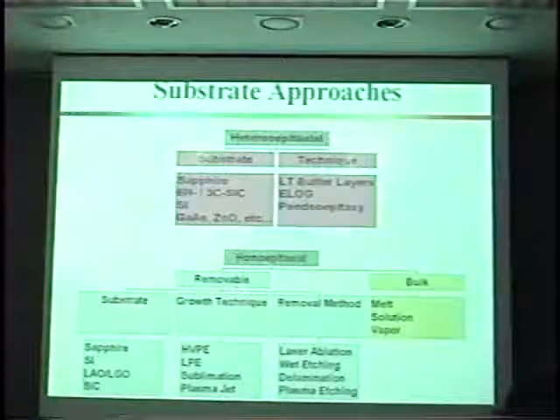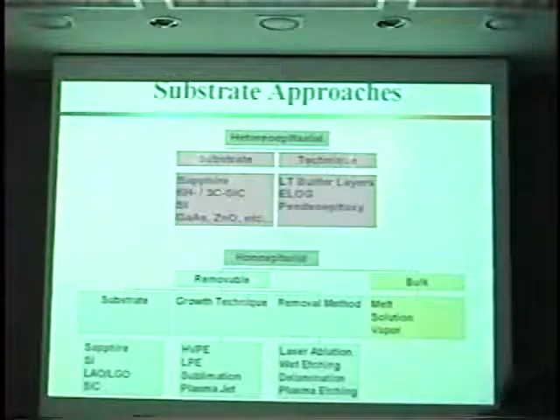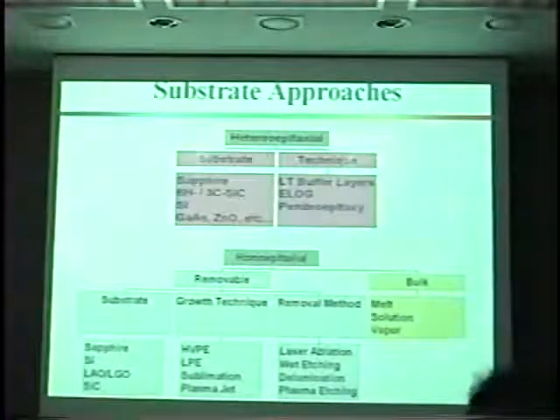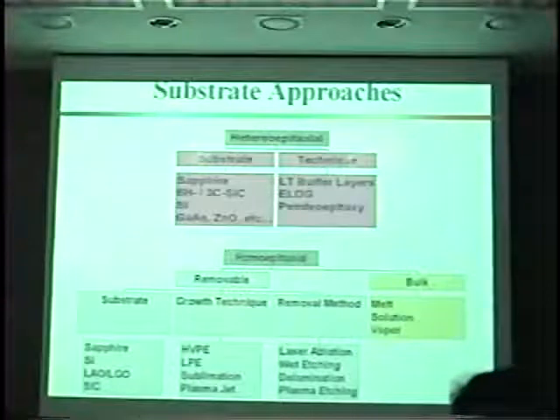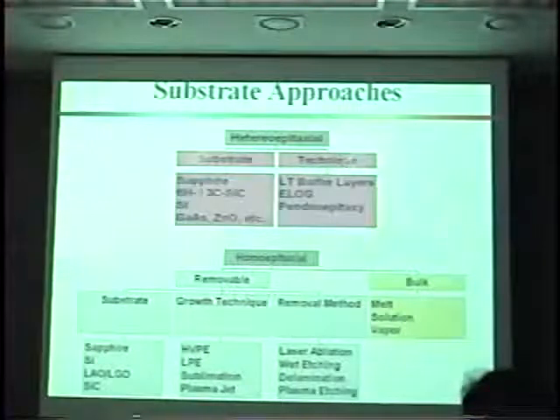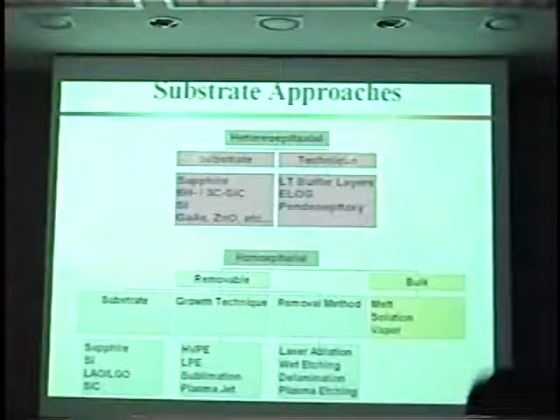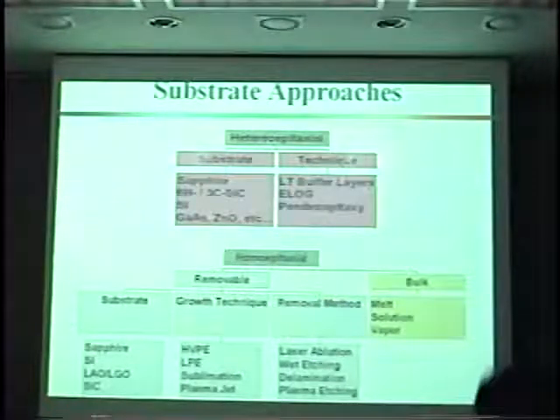Okay, I'm going to now talk about 3 or 4 subjects. The first one I'm going to talk about is the substrate issue. The problem with gallium nitride was for many years. Actually, there was a lot of work going on in the 70s to try to produce gallium nitride. At the same time, people were working on zinc selenide in the hope of getting blue. Zinc selenide is where most of the early success was taken. Unfortunately, zinc selenide is a rather soft material, and the quality of the material was not very good. There's also a problem with doping and p-type. But with the advent of high-quality gallium nitride and p-type doping, the gallium nitride work had surpassed the zinc selenide.